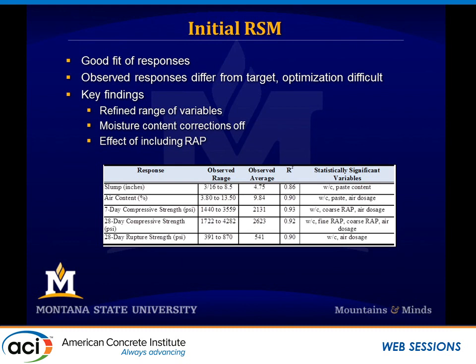We were trying to use a standard moisture content correction method of mix designs, and we found out that was not working. That was adding scatter to our data, and so we basically removed that and didn't do moisture content corrections afterwards, which seems a little crazy, but it actually helped us control variability by not adjusting for water, because that was adding a bunch of variability to it.